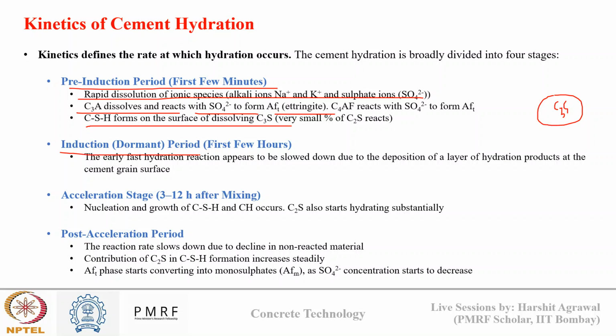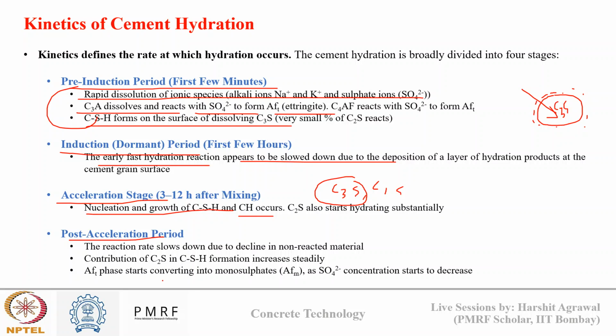Okay, then there is the dormant period, where this early rapid hydration slows down due to deposition of a CSH layer on the cement grain, which gives rise to the semi-permeable membrane that we talked about. Then there is the acceleration period, where there is a rise in osmotic pressure which breaks this semi-permeable layer, and there is nucleation and growth of CSH and CH. And now along with C3S, C2S also starts to hydrate, and then there is the post acceleration period where C3S hydration has almost completed, but C2S hydration gains speed. So there is more contribution of C2S to CSH formation. And if gypsum is consumed, then we'll see that ettringite starts to convert into monosulfate as the gypsum quantity starts to decrease. Okay, so this is how there are four different periods in hydration of cement.